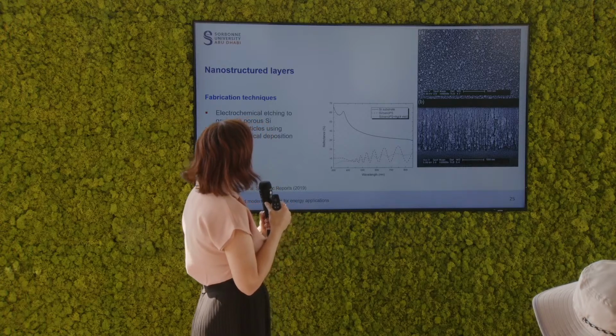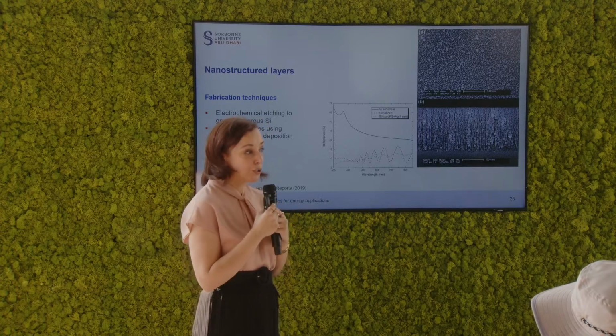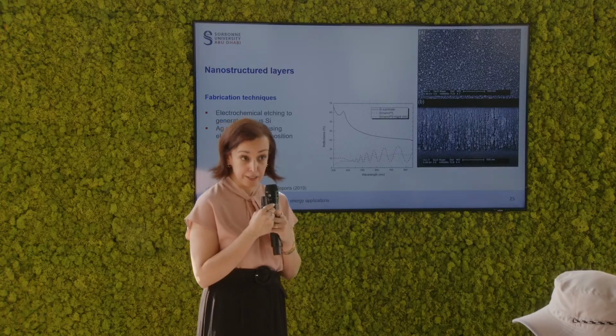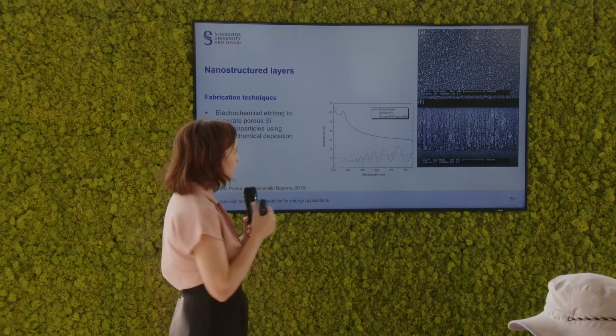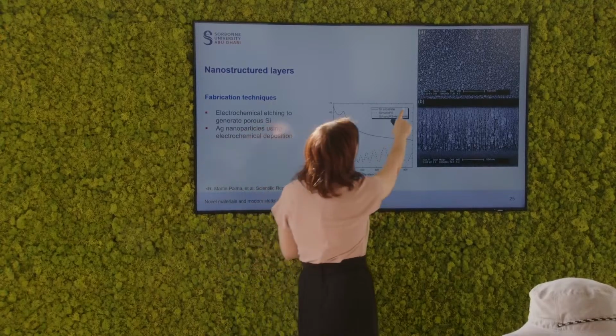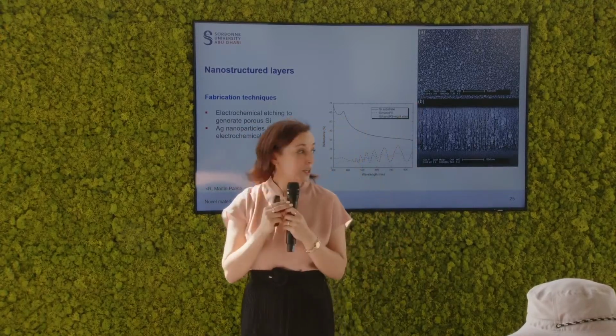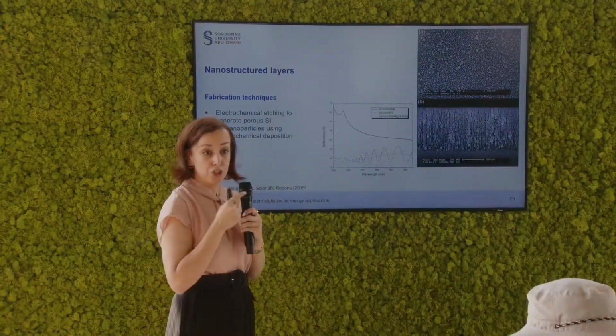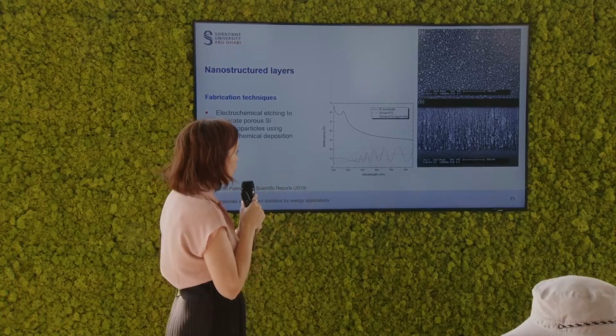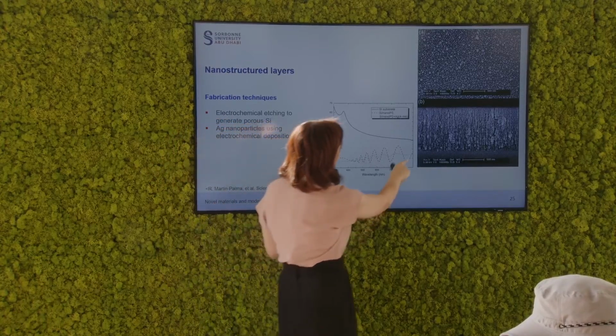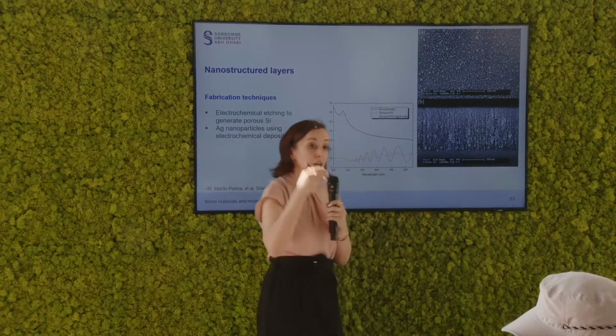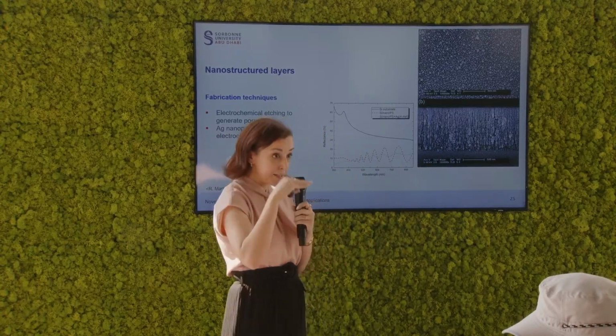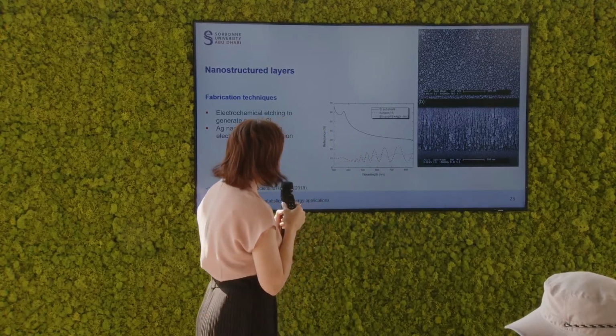You'll see that what they use here is an electrochemical etch of silicon to generate porous silicon. The top image here is the silicon layer with nanostructuring on the surface. It's no longer a smooth layer. And this is a cross-section microscope image where you see the nanostructuring as the depth of the layer progresses downwards.